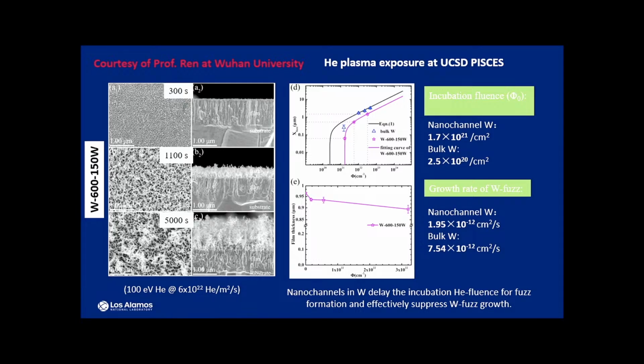Then we subject one of those good ones to the plasma exposure. This was done in the UCSD PISCES facility. You start to see this fuzzy structure form, fuzz form, as a function of the irradiation dose there. However, if you look at the comparison between this nano-channel tungsten versus the bulk tungsten, we actually delay this fuzz formation quite significantly. The minimum fluence required to initiate the fuzz process, versus the fuzz growth rate, has been changed there.